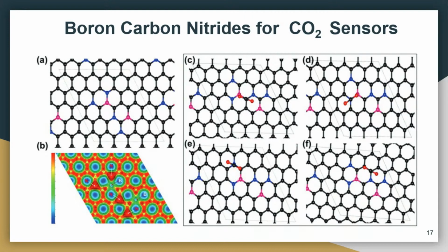But that was what we believed. We are expecting some molecular docking effect, I mean, for charge transfer. But fortunately or unfortunately, what we are getting is that this can act as a better sensor for CO2. Because compared to NH3, CO2 has a higher adsorption energy, and the experiment also proves that. So we took the CO2 system to match our experimental findings. And we calculated the different adsorption orientations. Not only vertical but horizontal also, we did a lot of things, and we analyzed with respect to different distances also.